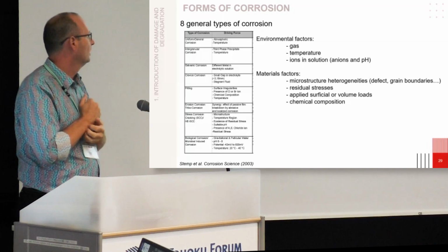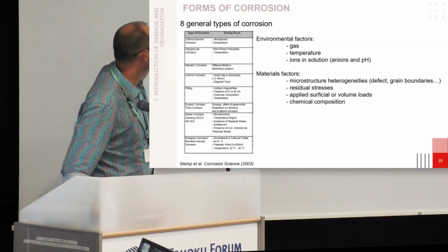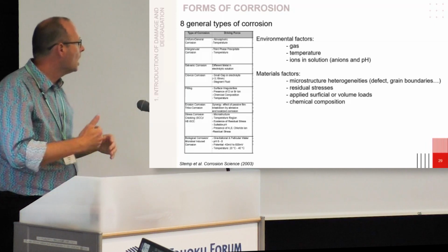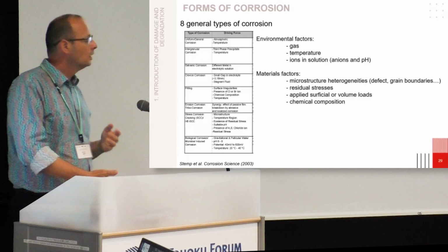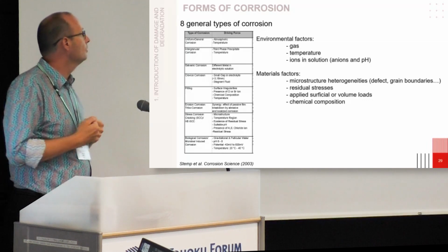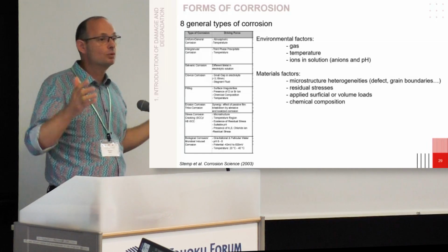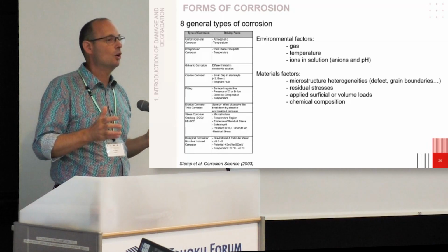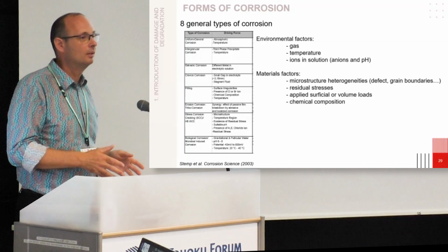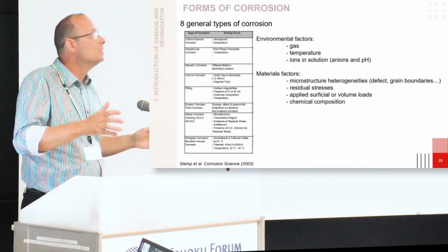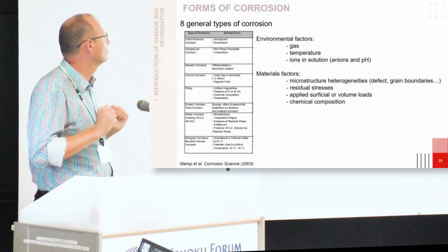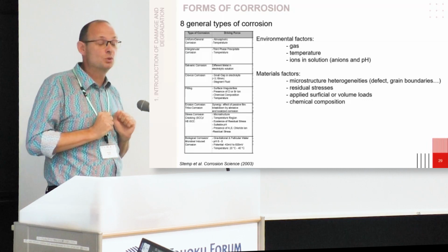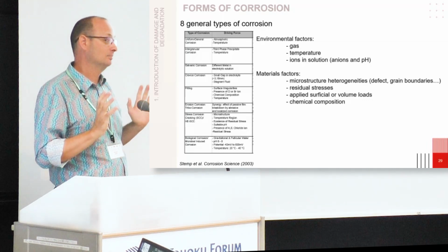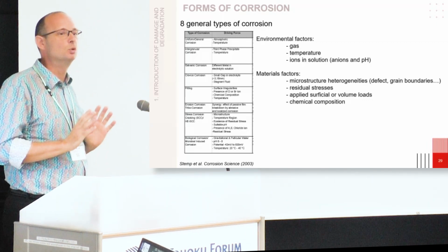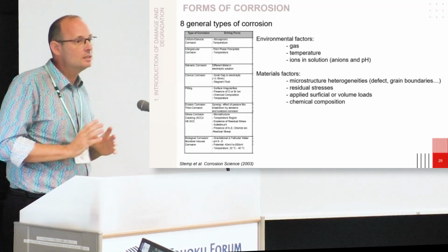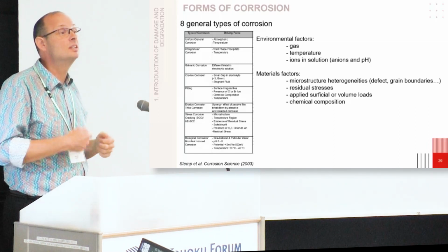That's for the environment. So you can have a look rapidly everywhere. You will find at least one of these parameters that has a stronger effect than the others. Regarding the material, we always have the same microstructure heterogeneities. Until now, it costs a lot to create monocrystals of materials. It should be interesting for mechanical properties, I don't know, I don't come from mechanics. But from the corrosion viewpoint, yes. If I have a monocrystal without any defect, it starts to be very good. So the microstructure itself of the material will act on its degradation regarding corrosion.